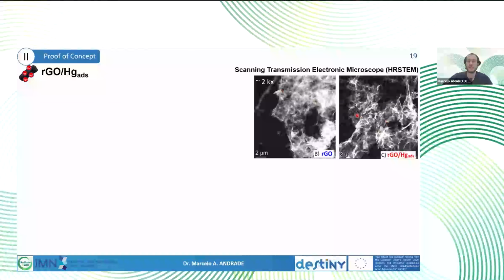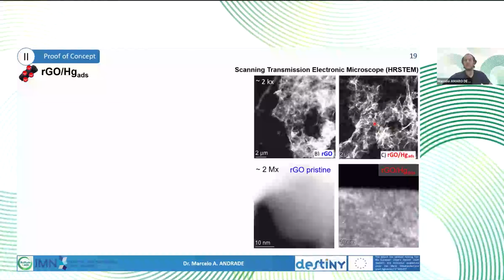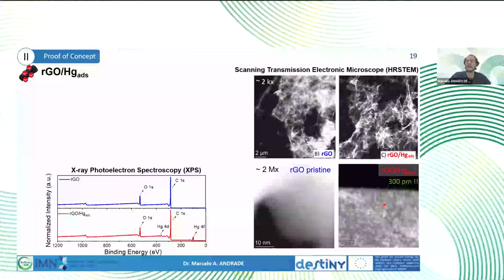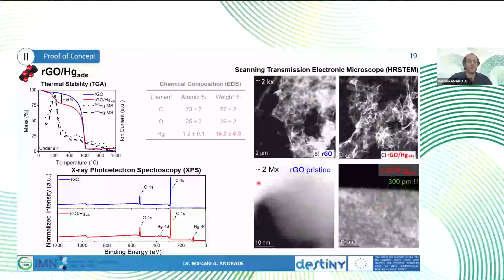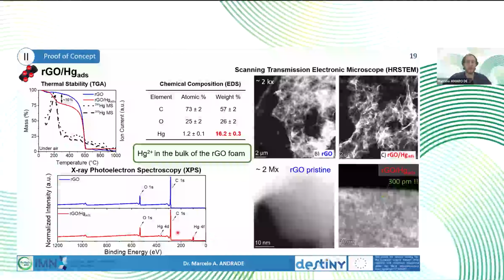We do not see at this magnification a major difference, but once we zoom in further, we start seeing some bright dots on the RGO with mercury, and they measure around 300 picometers, and that was associated to the mercury adsorbed on the surface, since you have a very high contrast between carbon matrix and mercury. Also, XPS detected the presence of mercury without nitrogen. So mercury 2 was indeed adsorbed, and it was not just deposited in the form of a salt or nitrate, since in the origin solution.